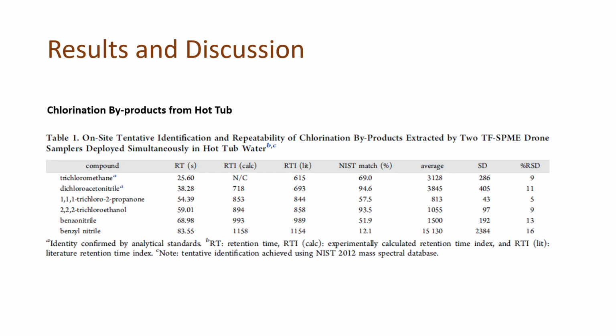In terms of analytical performance, the percent relative standard deviation for the 6 chlorination byproducts identified was quite reasonable. It ranged from 5% for 1,1,1-trichloro-2-propanone to 16% for benzyl nitrile, and is given in the table.